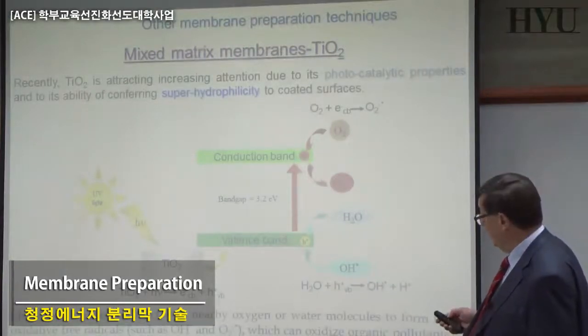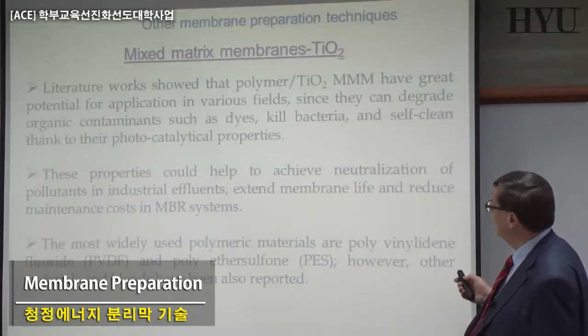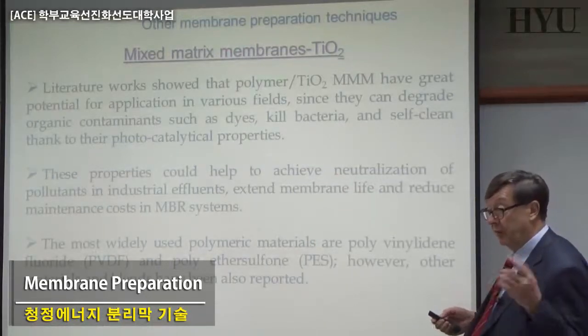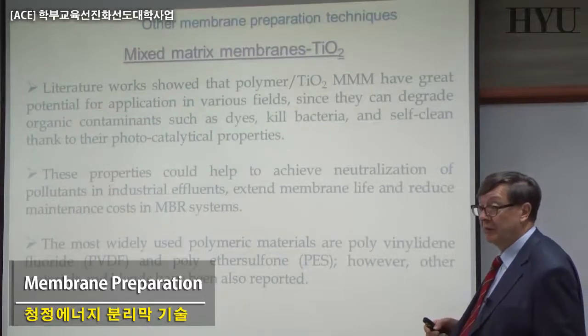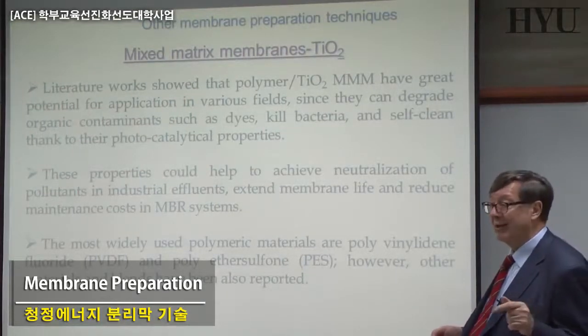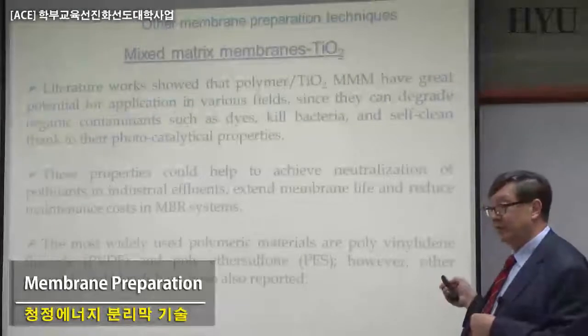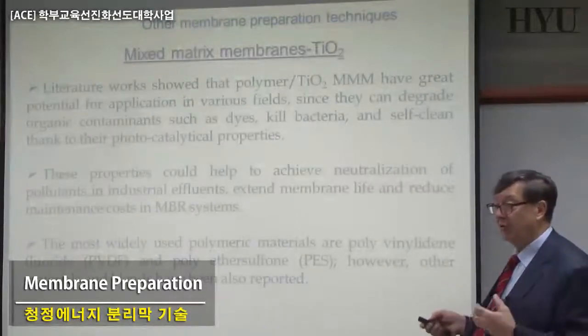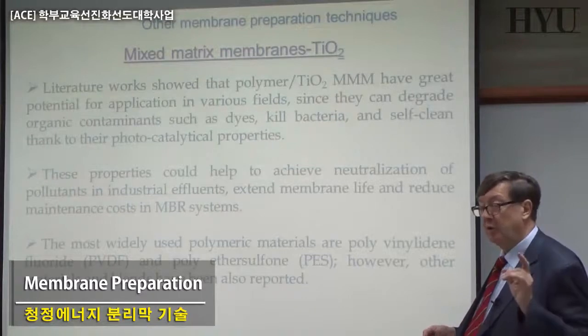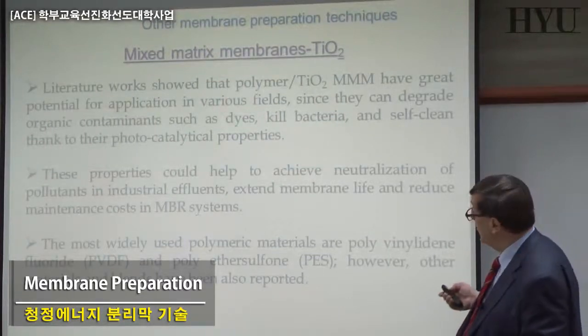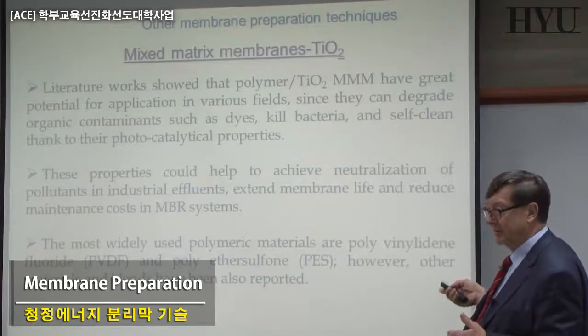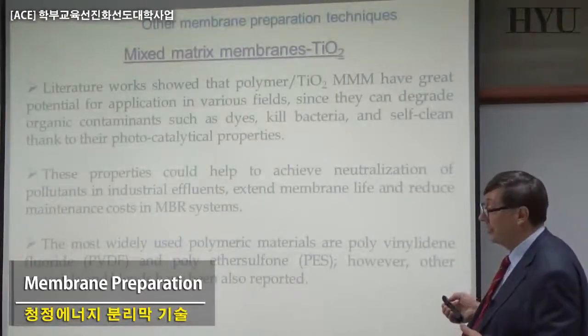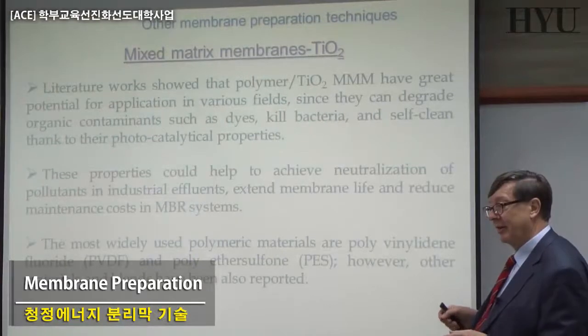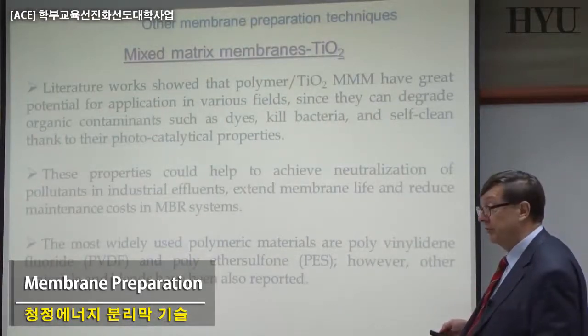So this is quite interesting, and starting from this, people are trying to prepare titanium dioxide mixed membranes. If you go in literature, you will find in Europe there is a big project today, called NAWADEX, where we are involved, in which you are using titanium dioxide ultrafiltration membranes to try to optimize reverse osmosis. It's a way to better control fouling. So in the pre-treatment, not only are you using UF, you're using UF with special membranes. This is a mixed matrix membrane where titanium dioxide and some other stuff is inside, and it is eventually complicated, but this is a way of doing.